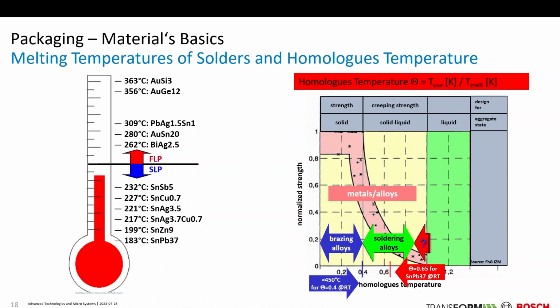And looking at this standard alloy, tin-lead, at room temperature it is already 0.65. This is a really huge value regarding the application. It would mean, in comparison to stainless steel or something like that, that you have to apply a load of roundabout 600 or 700 degrees C. So the homologous temperature shows an indicator of the loading on your metal or your metal alloy. It's quite impressive in comparison to steel.